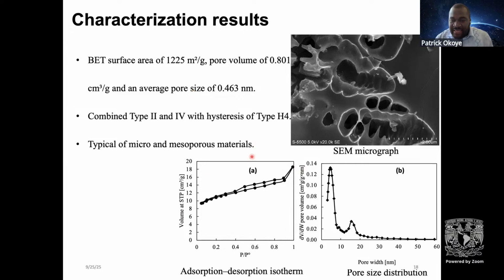When we looked at the isotherm, we found that, according to IUPAC, the International Union of Pure and Applied Chemistry, we have a combined type 2 and 4. Type 2 is in the lower region of the relative pressure and type 4 in the upper part, with some space between the adsorption and desorption. This space is due to capillary condensation, and it is type 4 hysteresis, they call it. And for the distribution of our pores, we found that we have pores from about 1 point something to about 8 nanometer.